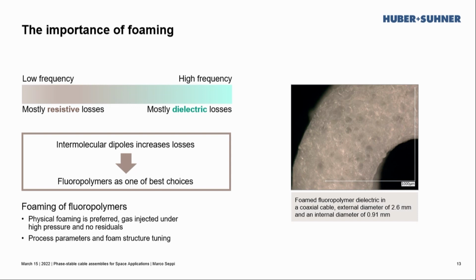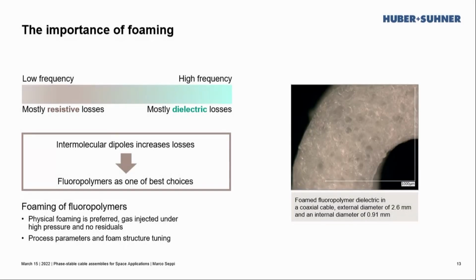Why is the dielectric characteristic so important? Well, when we are working in low frequency, most of the losses in coaxial cables are of the resistive type, and therefore they are linked to the construction of the cable, but they don't have a huge effect on the dielectric. On the other side, when it comes to the insulation, it is at high frequency that the importance is at the highest, and there is where the dielectric losses are the highest. The reason being that there are intermolecular dipoles which imply that there are losses in the signal, and therefore the fluoropolymers, because of their chemical characteristics, are one of the best choices.